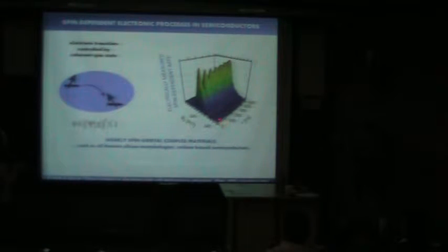Then what you see is, for most magnetic fields, and I could extend these axes, you see nothing, so there's actually no current response at all. What that means is this plot represents a current change: there's a current the whole time, but what is plotted here is the change. And there's no change whatsoever, no response to that pulse. But then there's one particular magnetic field, in this case 345 millitesla, where you do see a strong signal. The longer the pulse is, the higher it gets, and it reaches a maximum, then a minimum, maximum, etc. Obviously this is some sort of decaying oscillation.